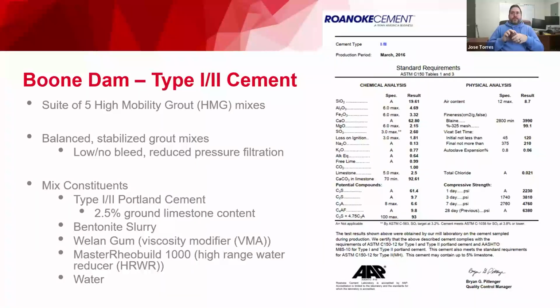I put the mill certs for that cement here on this slide. This mix had about 2.5% ground limestone content. Typical cements before this 1L came through allow up to 5% limestone content generally. But in the mix also was bentonite slurry. At the time, we used Welan Gum as a viscosity modifier and to help control bleed, as well as MasterRheobuild 1000 and water in the mix.